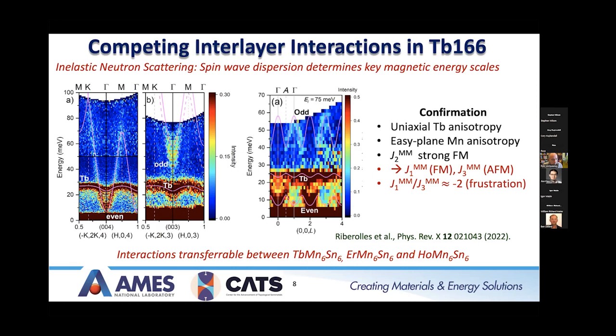Looking at another cut here, along the OOL direction, you can clearly see the gap between the even and odd branches, and then you see the terbium branch lying in between. So our fits basically confirmed that we have this uniaxial terbium anisotropy. I should say all these data were taken at 6 Kelvin. This is the low temperature state where the ferromagnetic order is along the C-axis.